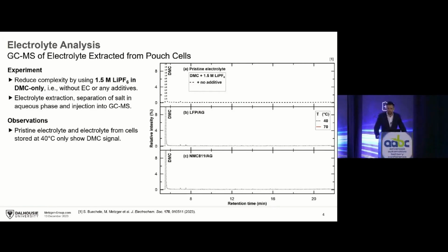So the top panel, panel A, shows you the pristine electrolyte. And you know there are of course no species formed because that electrolyte was never in the cell. And we just see the DMC peak here at the low retention times, right? So and then in panel B and C, you see the electrolyte we extracted from LFP graphite cells and NMC 811 graphite cells when they were stored at 40 degrees Celsius, which is sort of a moderate temperature. And you see there are no major reaction products formed here in these cells. But what if we store the cell at higher temperatures?